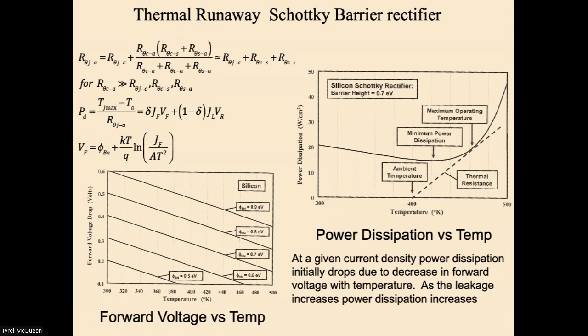So there's a minimum power dissipation, and now the temperature is going to start rising again. The thermal resistance between the junction and the ambient will determine this straight line. So there is going to be a maximum operating point after which this whole situation will go into thermal runaway. One of the things that will determine where that maximum operating temperature is going to be is the thermal resistance of the material. Thermal resistance has gotten to be such a big issue in high power microwave devices, high power devices, that it is a big influencer of the materials choices.